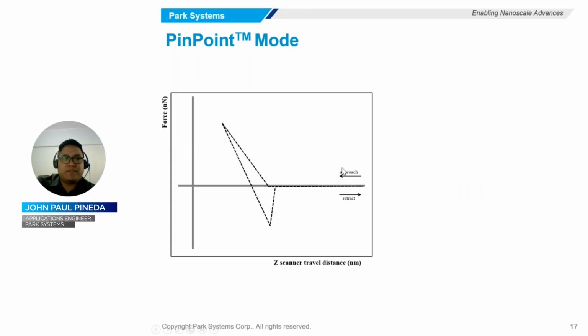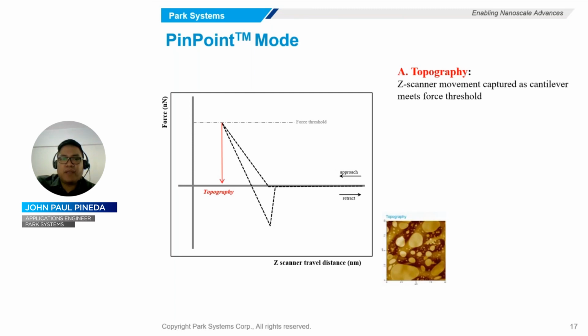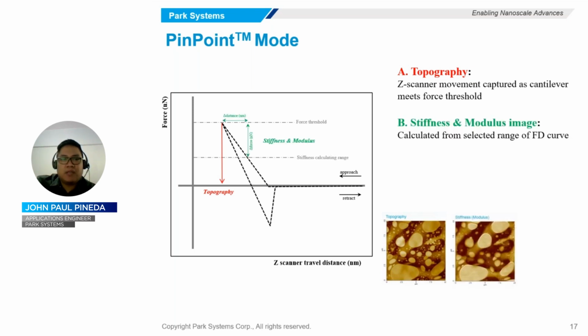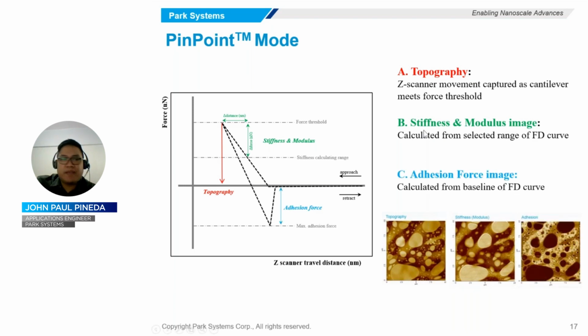So here is an FD curve collected from one single data point. From this data, stiffness, modulus, and adhesion can be determined by an automatic calculation process in the system. The topography can also be acquired simultaneously by monitoring the Z scanner movement as the cantilever meets the force threshold. The stiffness and modulus can be calculated using a selected range of the force distance curve. And then finally, the adhesion force can be obtained after calculating the maximum from the baseline of the force distance curve.